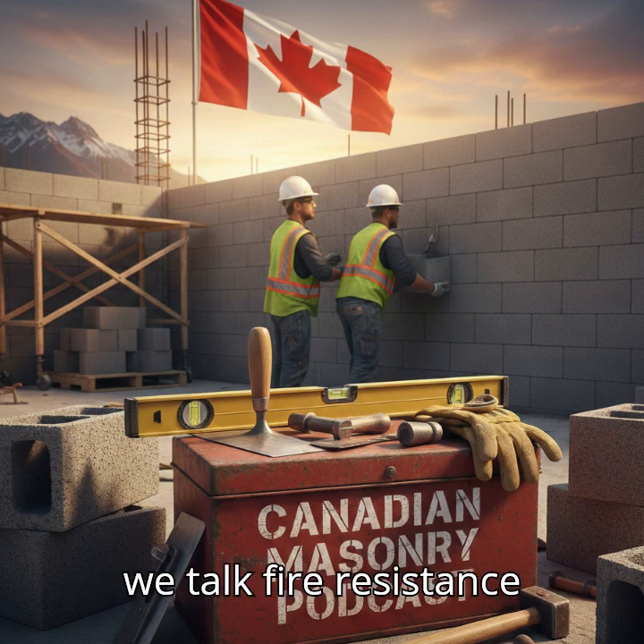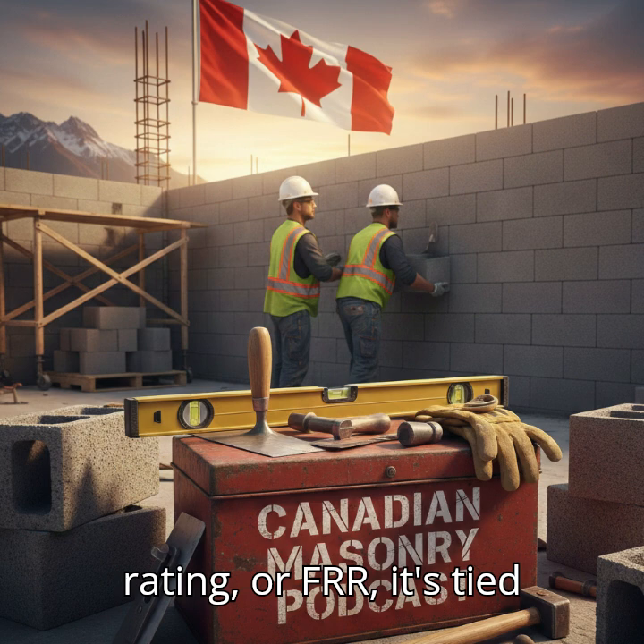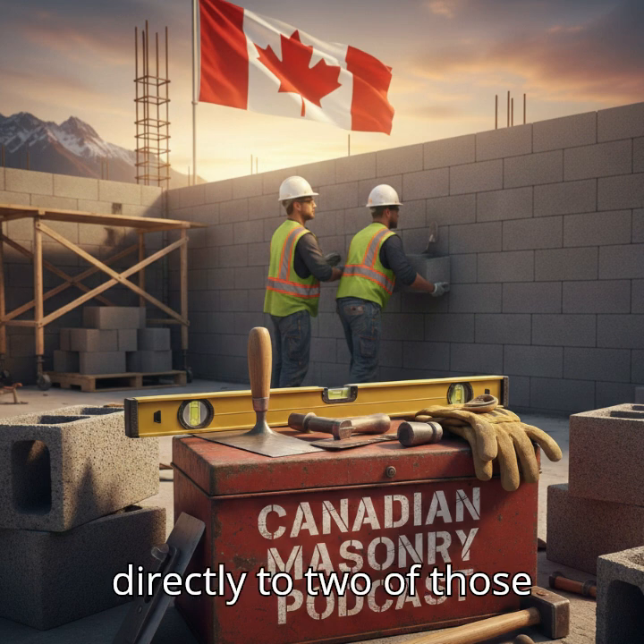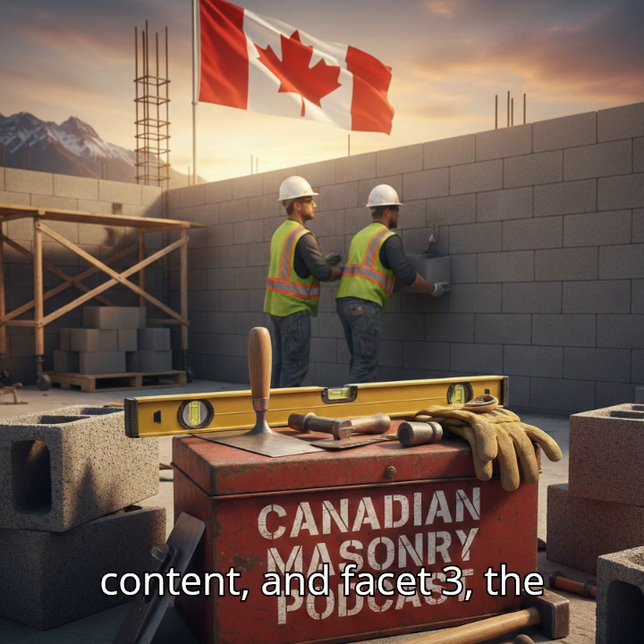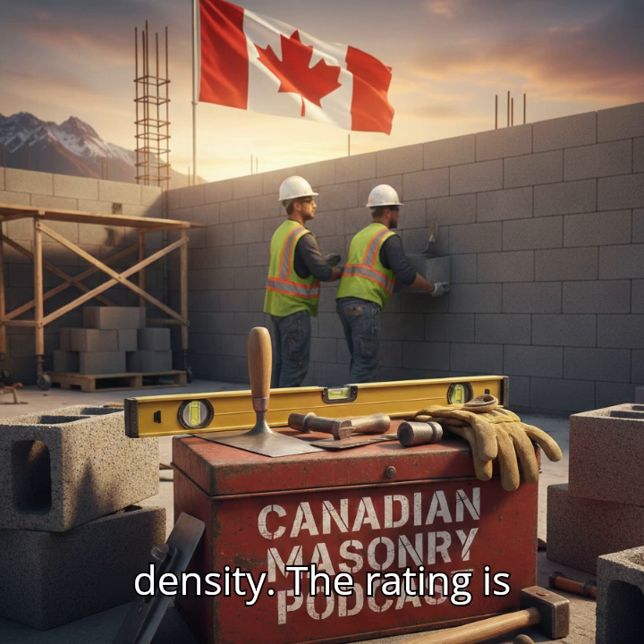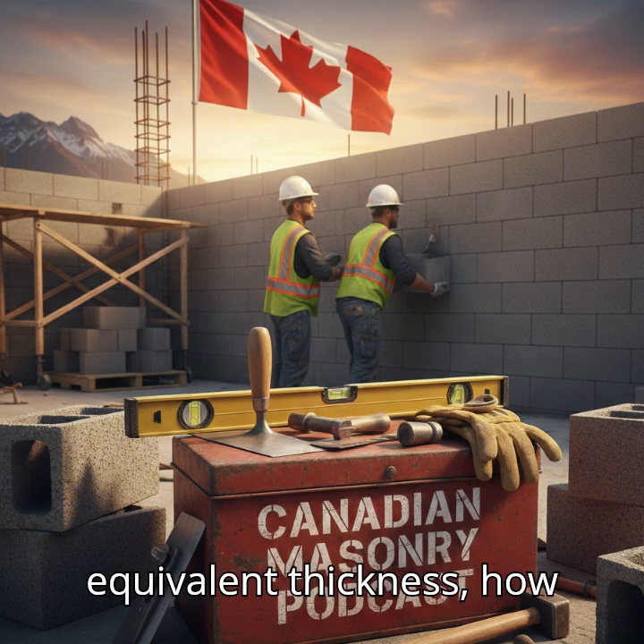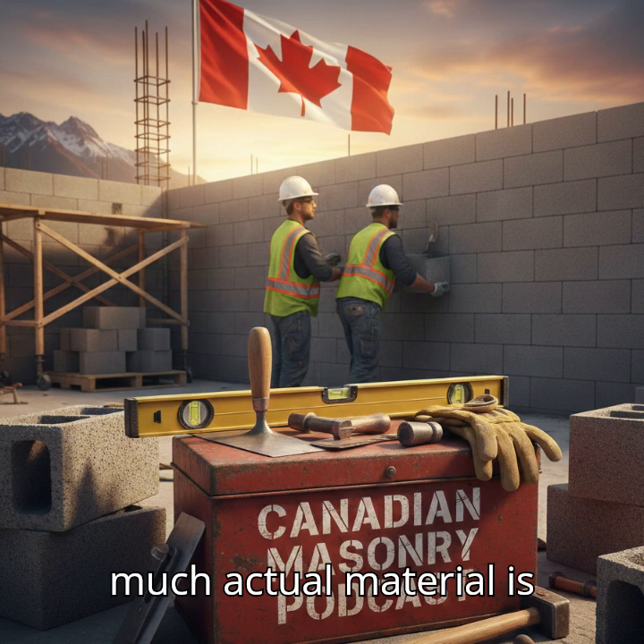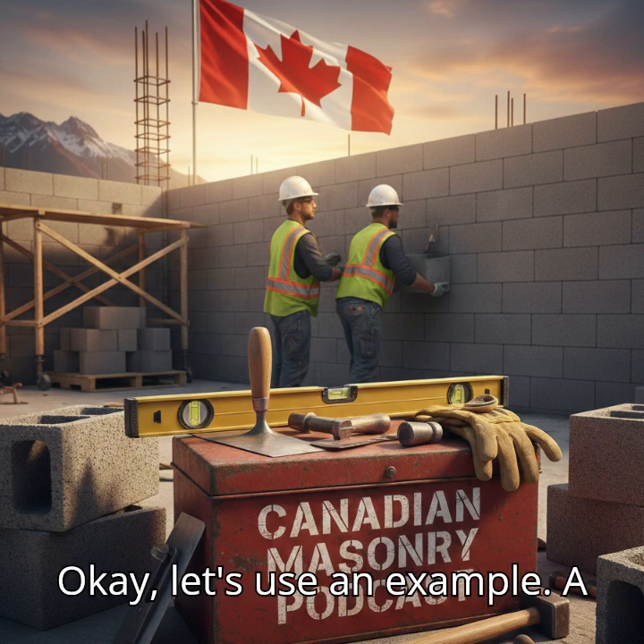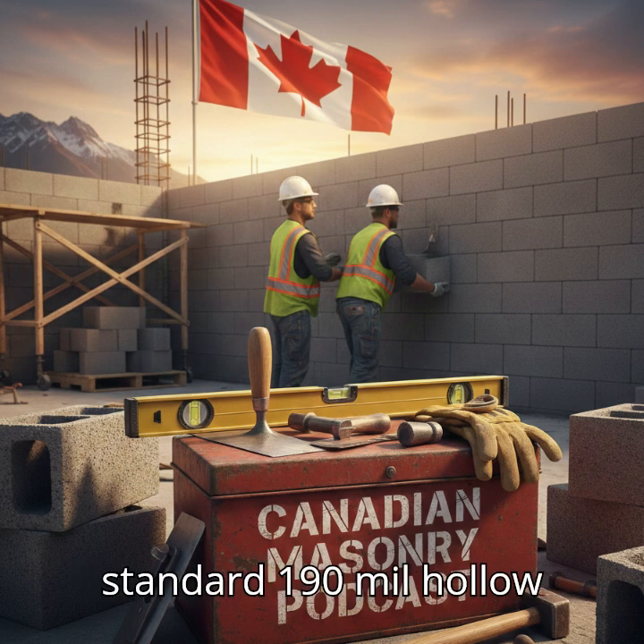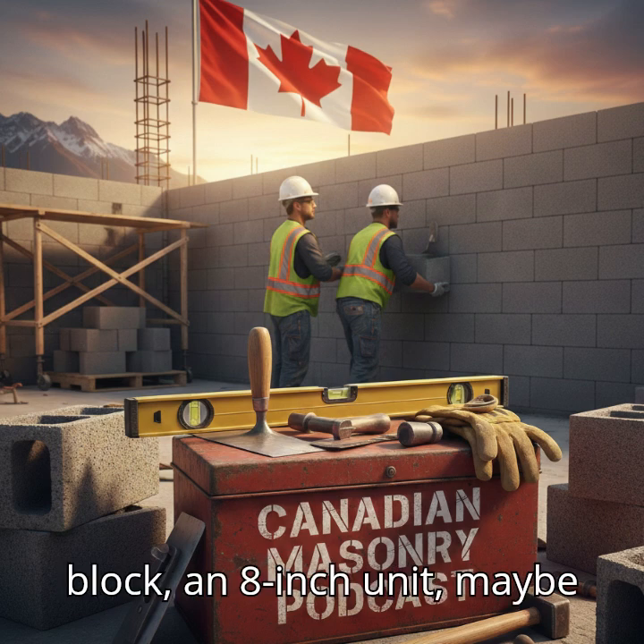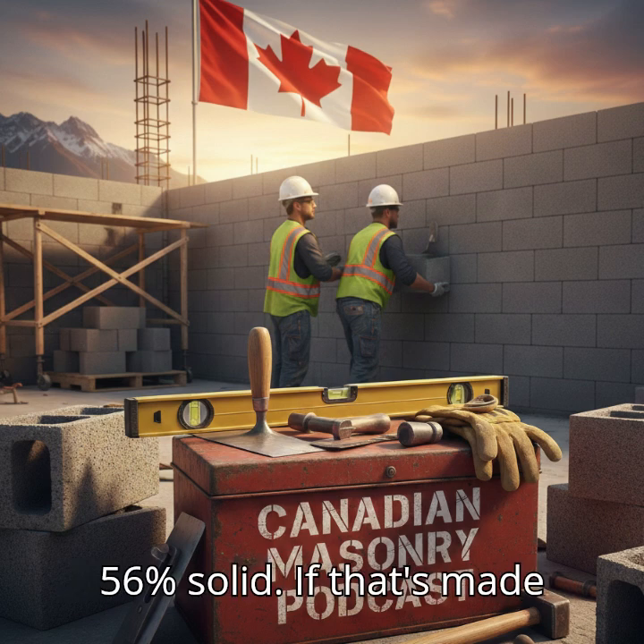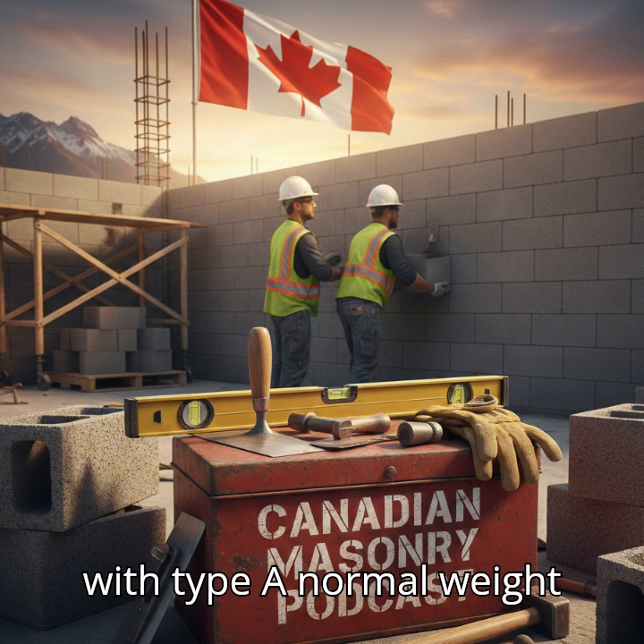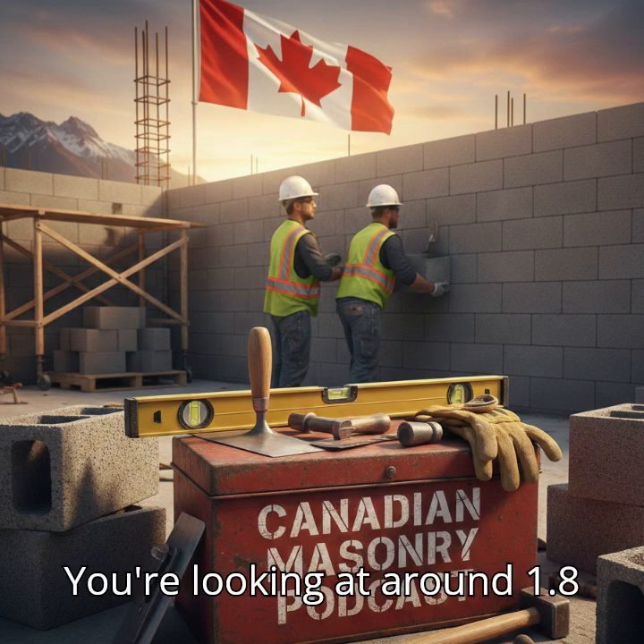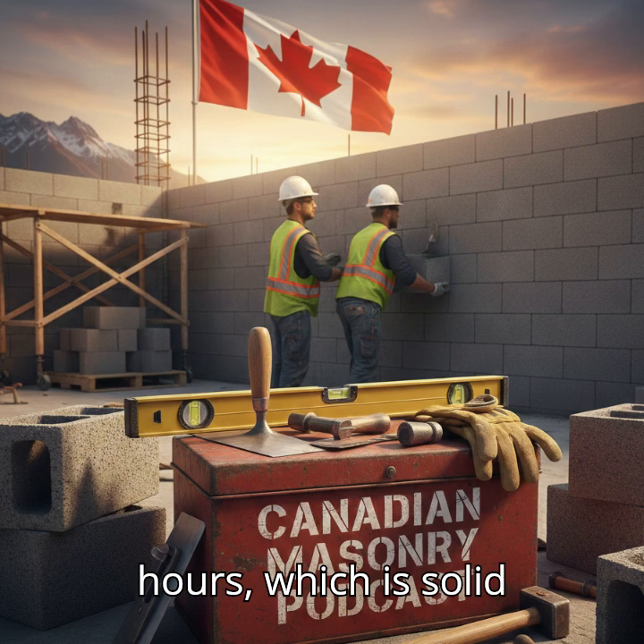Absolutely. When we talk fire resistance rating, or FRR, it's tied directly to two of those facets. Facet 1, solid content, and Facet 3, the density. The rating is determined by the unit's equivalent thickness, how much actual material is there, and the concrete type. Okay, let's use an example. A standard 190 mm hollow block, an 8-inch unit, maybe 56% solid. If that's made with Type A normal weight concrete, what's our FRR? You're looking at around 1.8 hours, which is solid performance.